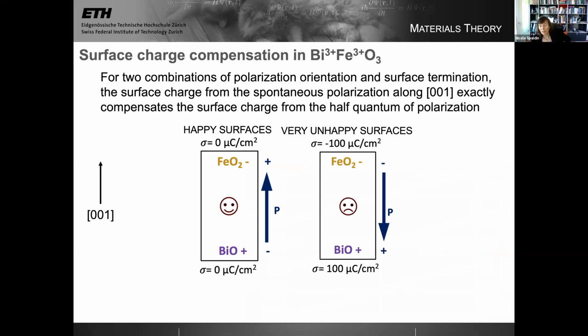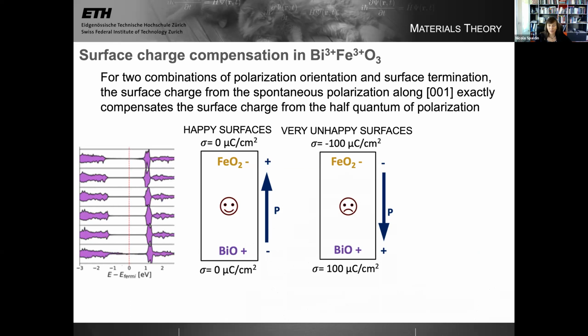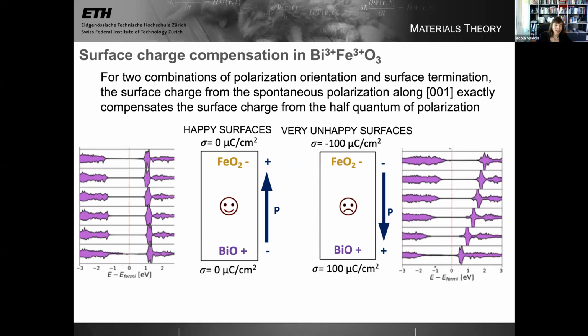The converse, of course, is if you try to switch the orientation of the polarization of bismuth ferrite, it's even more unhappy than in a conventional ferroelectric, because you have the surface charge from the polarization adding to the surface charge from the charged layers, and it's doubly as unhappy as it would be otherwise. This shows up in an electronic structure calculation.